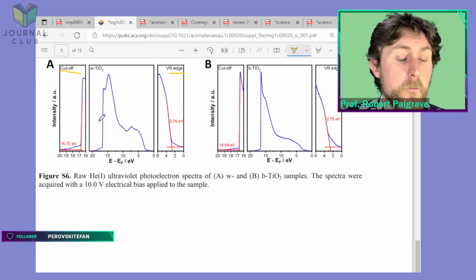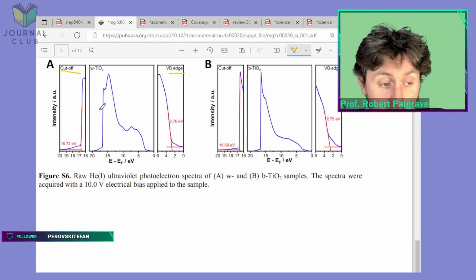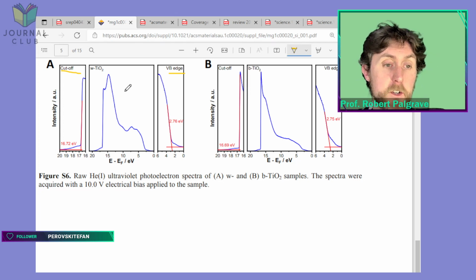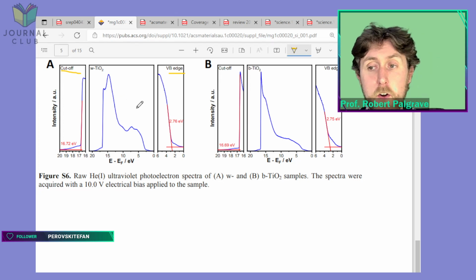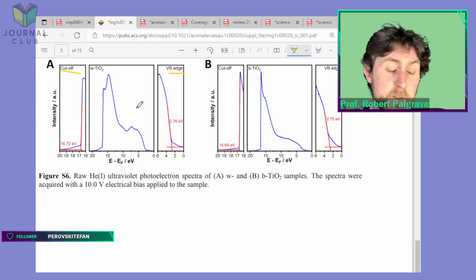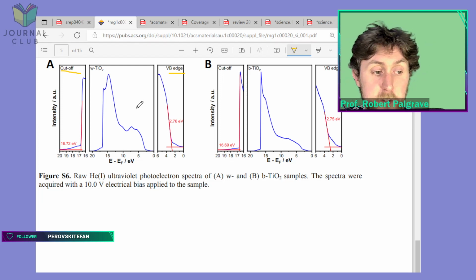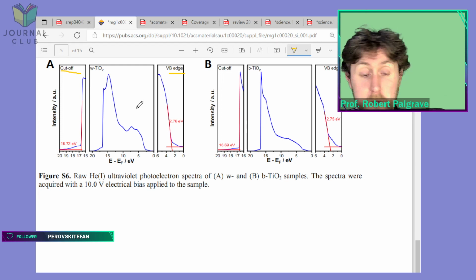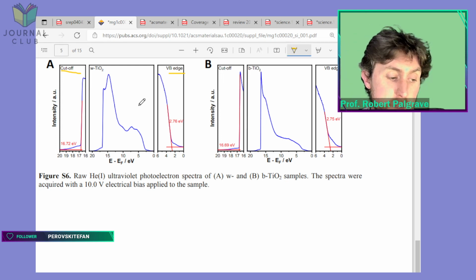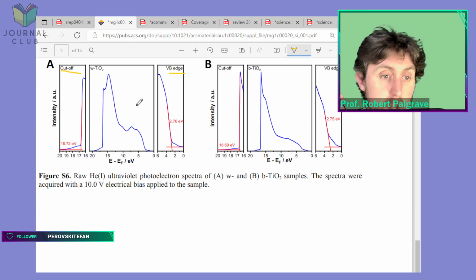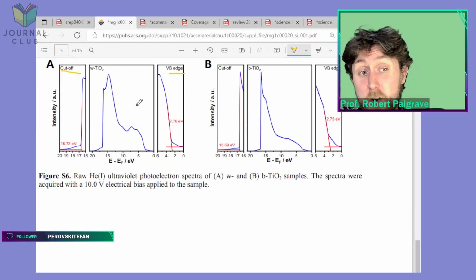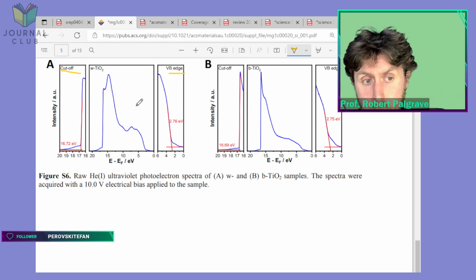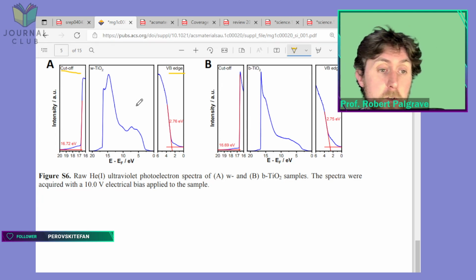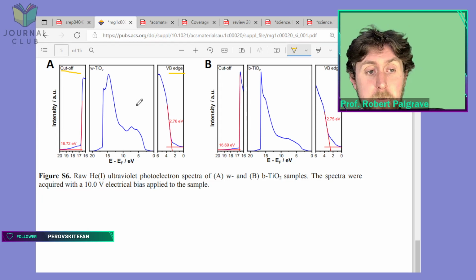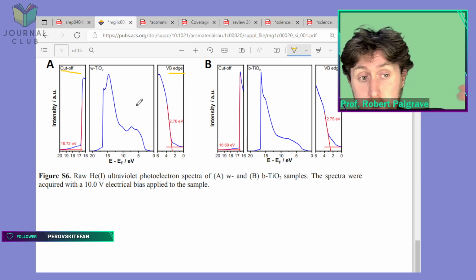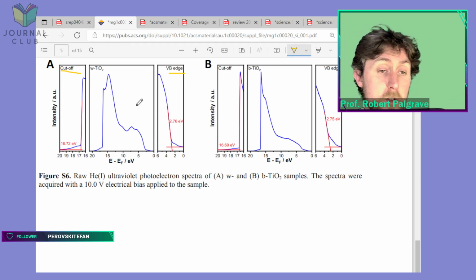A big problem with photo emission in general, but especially for helium-1 photo emission, is that you have a lot of other contributions to the spectrum that are not elastic photo emission from your occupied orbitals. So in normal XPS you have inelastic scattering. You have processes where electrons can lose energy while they're being photoionized, while they're being removed from the material, and you end up with a high binding energy background on your spectrum.